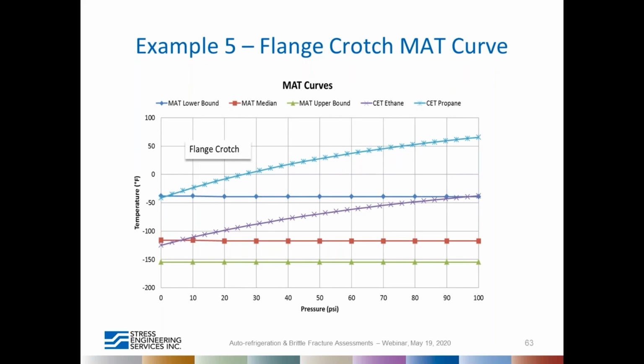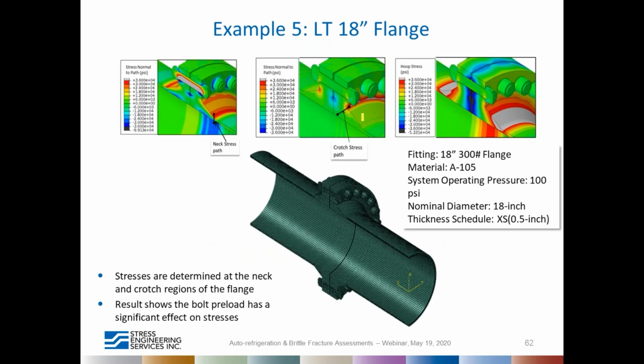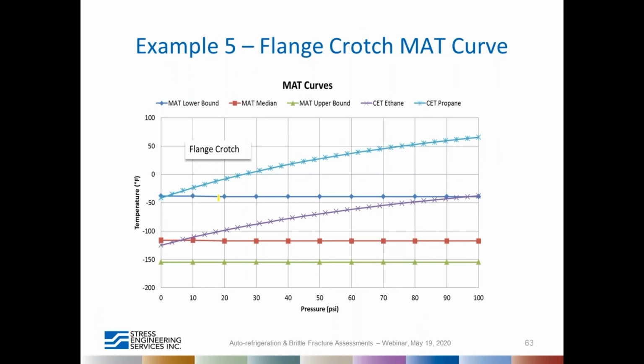And if you notice this for ethane, there's a spectrum of flash curves here, propane being at the warmest section and ethane being at the colder end. Ethylene is not included, that would be the lowest in this case, but ethane is a good example. However, if you look at one location in the flange, which is the crotch location here, it's hard to highlight it, but anyway, it's here. For that location, the MAT curves indicate a potential risk for brittle fracture.